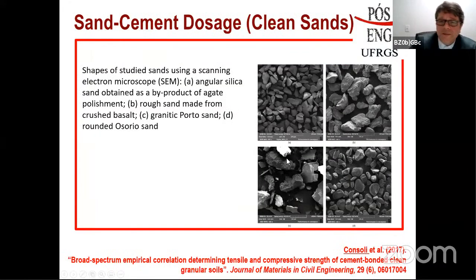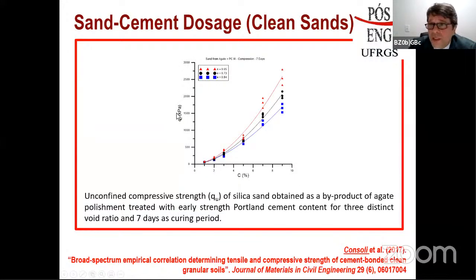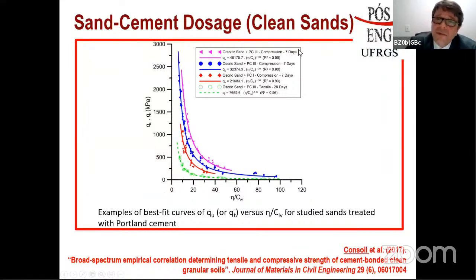Here is a paper from 2017 in which we tested different granular materials with different shapes, angularities and roughness. Some are quite angular, some are round, some are rough, some are not rough at all, from different places in the world and of different origins, four of them. This is qu, the unconfined compressive strength, against the amount of cement. We tested different curing periods, different cements, different soils, different amounts of cement and different densities too.